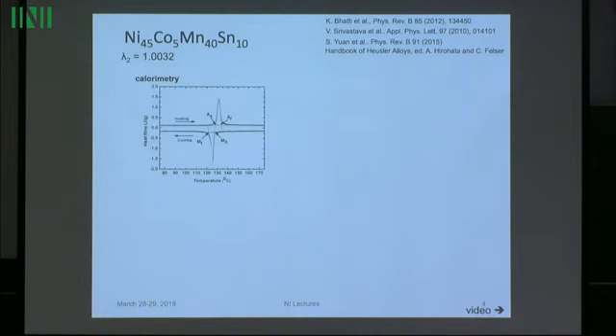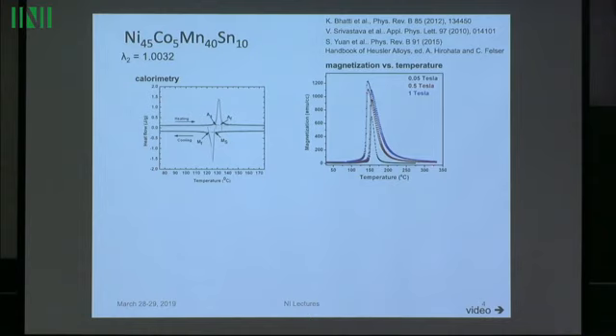So it has a fairly small hysteresis, maybe about 6 degrees. This is magnetization versus temperature. Now you can see it's been stabilized. The martensite phase is non-ferromagnetic, and now it transforms to the austenite phase without any strong field. This is just by changing the temperature. There's no applied field, and now we have this strong martensitic phase transformation. The austenite phase here is ferromagnetic, and if you continue raising the temperature, you reach the Curie point somewhere up here.